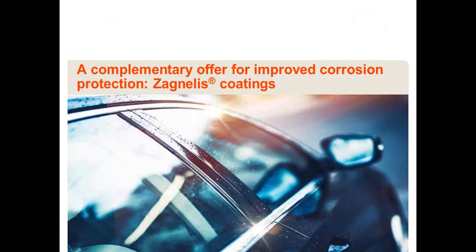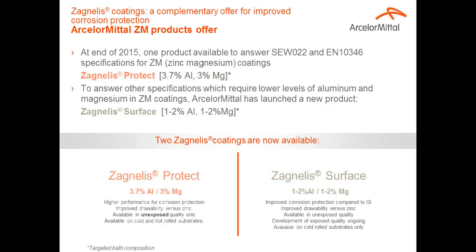So after those two coatings more dedicated to specific parts, I would like to make a highlight on the offer of ArcelorMittal on zinc magnesium coating. The brand name for zinc magnesium coatings in ArcelorMittal is Zagnelis. Up until the end of 2015, ArcelorMittal had one product available called Zagnelis, and it was okay with SEW022 and Euro norm, with the composition of 3.7% aluminum and 3% magnesium. From now on, this coating will be called Zagnelis Protect.